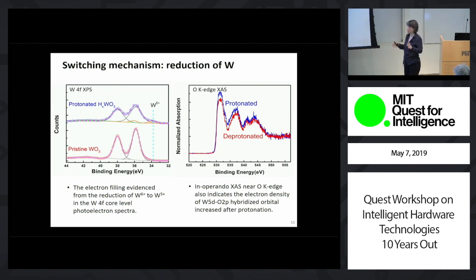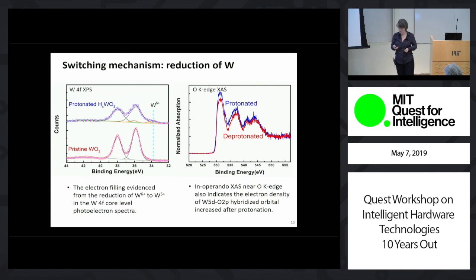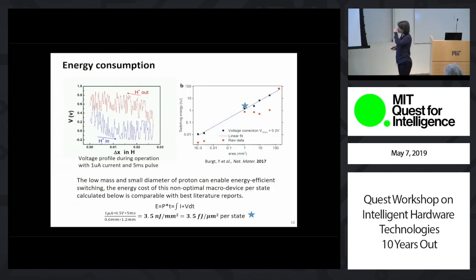So as long as we are within the single phase regime, that we are not over-protonating to change the phase, we can reasonably conclude that proton serves as an electron donor in tungsten oxide that gives rise to this electronic conductivity change. Okay? We have also looked into the energy consumption, and I must also repeat, this is our first set of devices which are rather large, on the order of hundreds of microns channel length, quite thick Nafion electrolyte layer, and so it's not ideal.